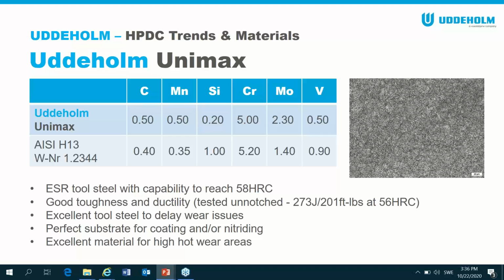If we look at Unimax here, Unimax is another tool steel that we make. This is like a son of Divar, so it's got more carbon in it, but it also benefits from a lot of the good ductility and toughness of Divar, not to the same level. There's a trade-off, but you get very, very good erosion resistance, hot wear resistance with Unimax, and its temper resistance is the same as Divar as well, but then you start at much higher hardness.